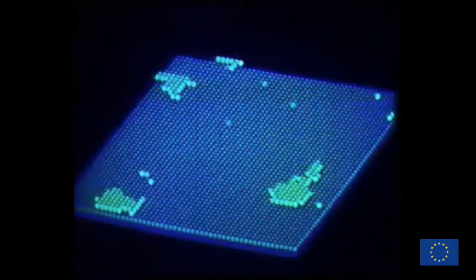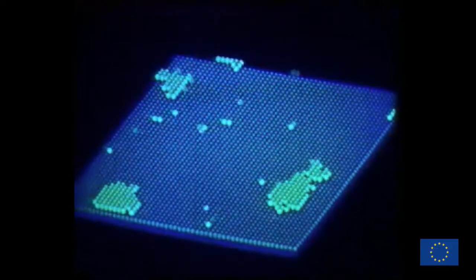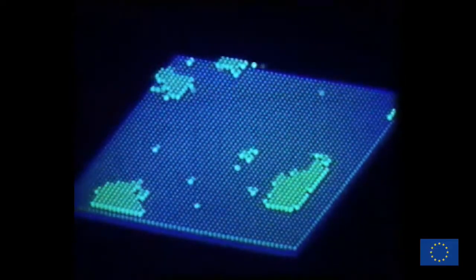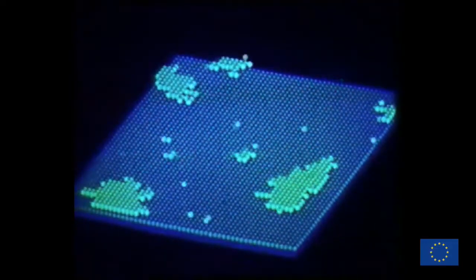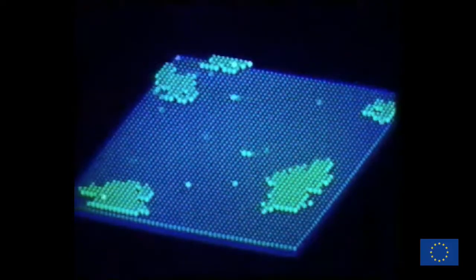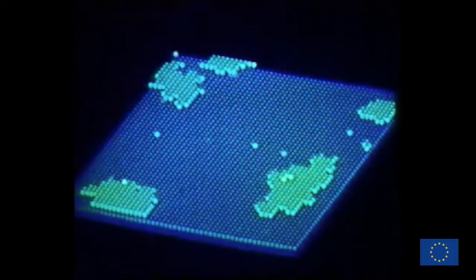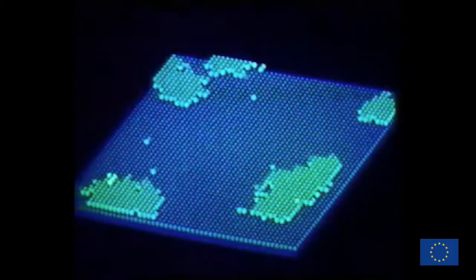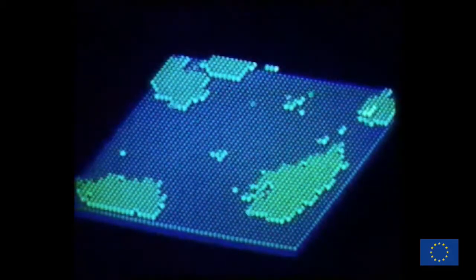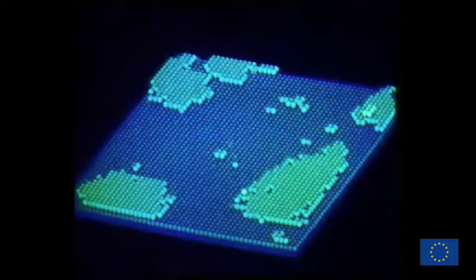So we have them here, and you see there are clusters that grow and then disappear again. Like this one here, it's gone. You have this one here. Will it maintain? It's exciting. Yeah, this one reached critical dimension, and it will remain. And then what you also will see is that you have these different nucleation sites. The longer you grow, you will see that they will start coalescing towards each other. So that's really how the first layers of the crystal start.